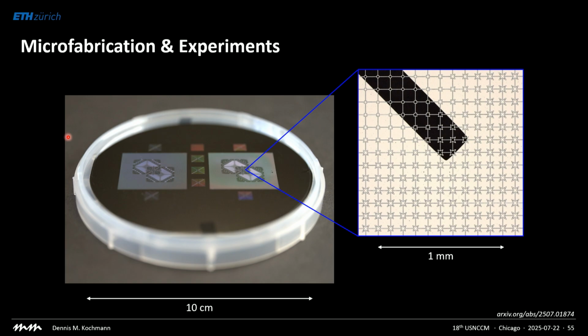So more recently, we've been using wafer-type fabrication techniques. In this case, all you do is you take a thin wafer, you pattern a structure into this. Because you use silicon wafers, this has pretty much no damping. Waves will go forever. We can make unit cells as small as a few microns. In this case, we can fit millions of unit cells onto a 2D wafer, and you can really print those designs that I just showed you, where your unit cell changes from one point to the other.